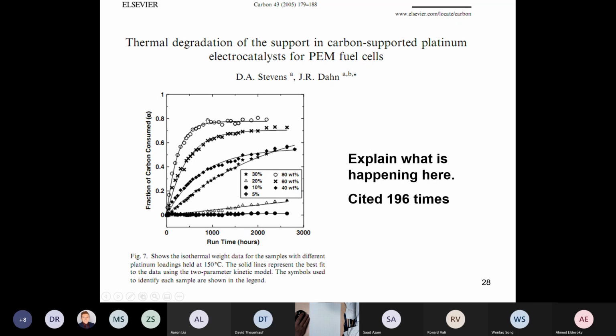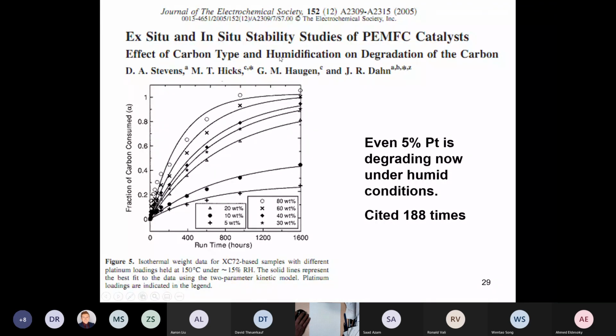So people in the fuel cell business didn't appreciate this particular issue, and it led to some interesting stuff, which I'll get to as we go along in the next couple of slides. So then we thought, well, wait a second now. Not only are you in the presence of air, carbon, and platinum, but you also have humidity, because you've got the water that's being created in the fuel cell. So Dave did the experiment again where the oven was held at 15% relative humidity. Okay, so 150 degrees C and 15% relative humidity. That's quite a high moisture content. But then you can see that even the 5 weight percent sample is degrading pretty rapidly, under these humid conditions.